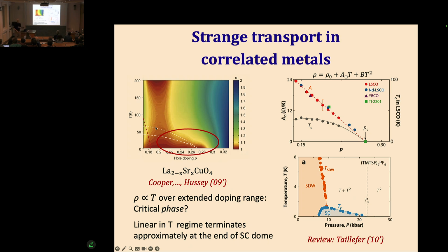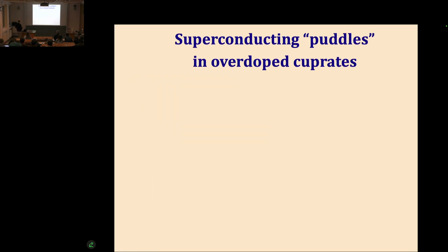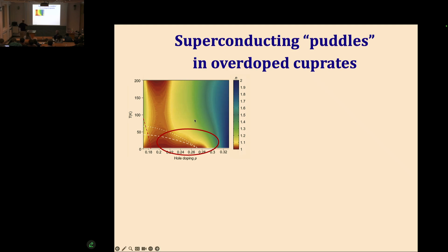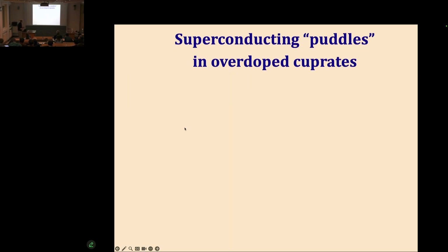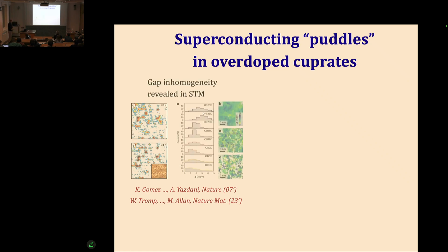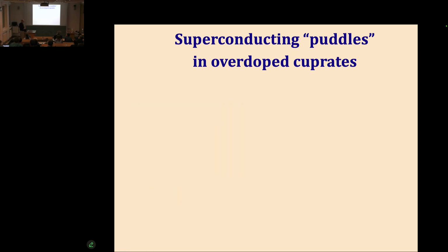causality and to say, well, it's somehow the remnants of the superconductivity that exist even if we suppress global superconductivity that are causing the linear T scattering in the normal state. And we want to take the second point of view. We want to focus on this extended low temperature regime of linear T resistivity, and interpret it as remnants of superconductivity that survives even beyond the point where superconductivity globally is destroyed and are causing this linear T scattering.